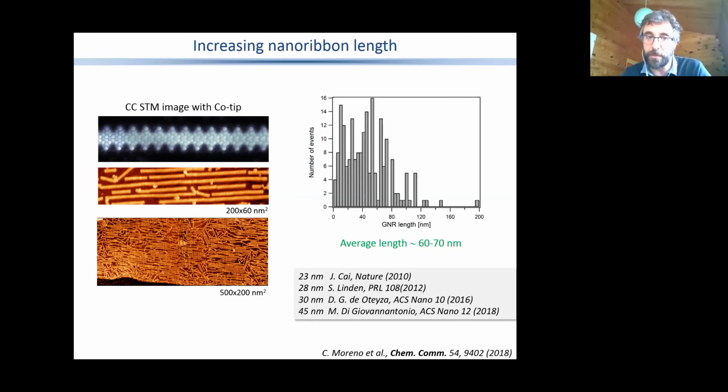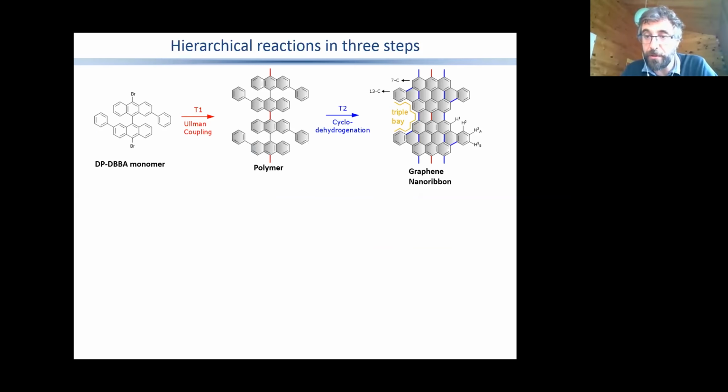So far, there was no controlled covalent assembly of these nanoribbons, because the only way of aligning them was by using these steps. Also because of the particular edge structures. If you covalently align 2 armchair ribbons, you get just the same armchair ribbon, but wider, okay? In our case, we had all the conditions to have an interesting structure. We had the alignment of the ribbon, which is related to the particular interaction of the monomer and the surface. But we also have this interesting edge structure, okay?